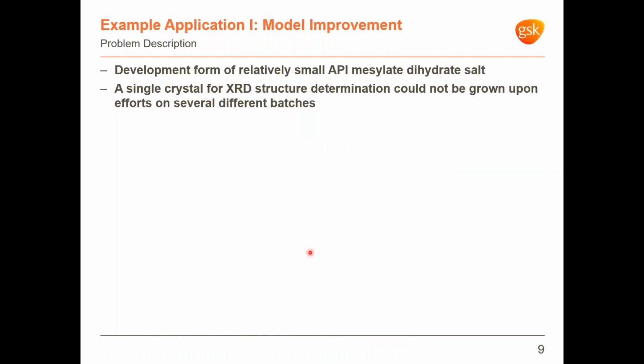I will now present an example where this workflow was successfully applied, in this case to improve a structural model obtained from XRPD structure solution, which presented suboptimal hydrogen bonding interactions. The compound in question is the development form of a dihydrate mesylate salt API. As it happens, a single crystal suitable for XRD structure determination could not be grown despite several efforts made.